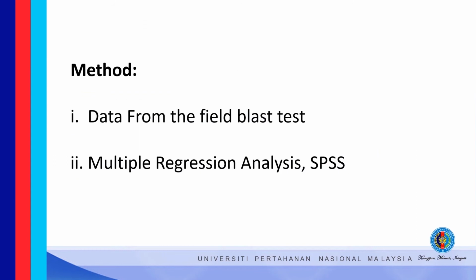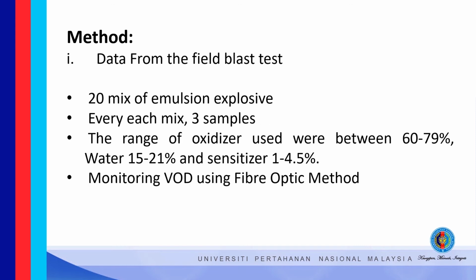The method for this paper: first is data from the field blast test, and second is multiple regression analysis from SPSS. Method 1, data from the field blast test. There are 20 mixes of emulsion explosive. Each mix has 3 samples, and the range of oxidizer used was between 60 to 79%, water 15 to 21%, and sensitizer 1 to 4.5%. Then VOD was monitored using the fiber optic method.